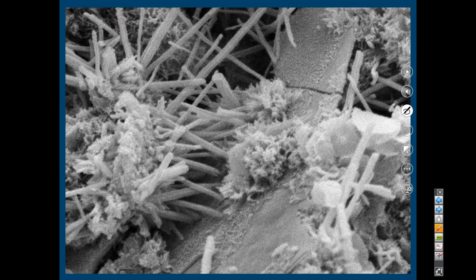So if we're looking at concrete on a very small scale, like we see here, now this is where we're using scanning electron microscope or some of this new technology that we're able to examine concrete on a very small scale. Now we're able to see, well, this is CSH here, the calcium silicate hydrate formation. That's CH. The CH is typically formed like in platelets. So the calcium hydroxide, there's some CSH growing on the CH platelet. And then those rods that we see there are ettringite, which tend to form earlier on in the concrete and then break apart as the concrete continues to mix and cure. And then everything in between, you see these large voids here, those are voids. And some of that will get filled up as hydration continues, but not nearly as much as we'd like.